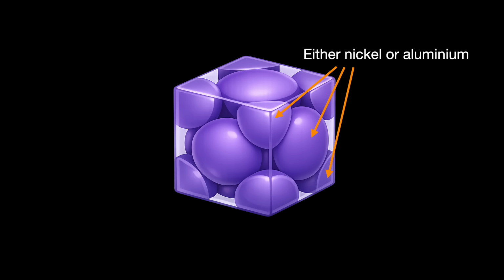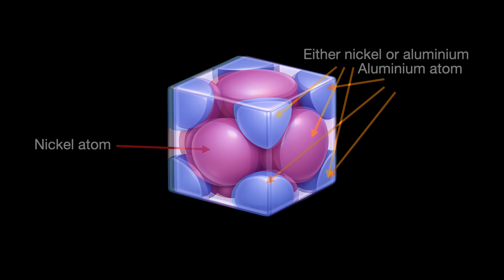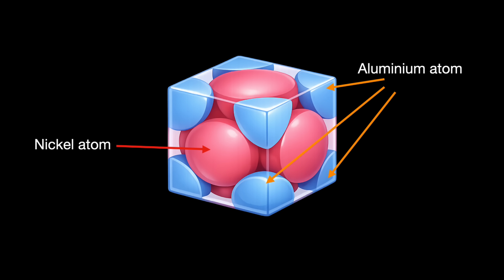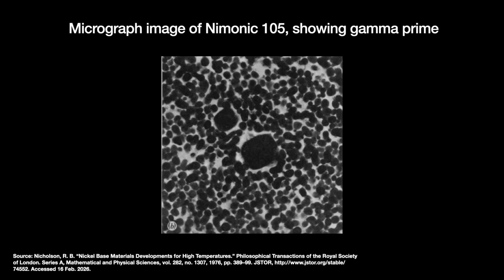Grains are made up of quote-unquote unit cells featuring a 5-atom cubic structure, 4 atoms at each corner with 1 in the center. Normally, you can have either an aluminium or nickel atom mixed up at any one of these 5 positions. These cubical arrangements, or phases, are called just gamma, not gamma prime. Gamma prime, on the other hand, is a very specific phase, 4 aluminium atoms at the corners and 1 nickel atom at the center. This is way more ordered. Gamma prime adds friction between the sheets of metal atoms, thus making it harder for a dislocation to travel through it, impede the dislocations, and we hinder and slow the progress of the creep.